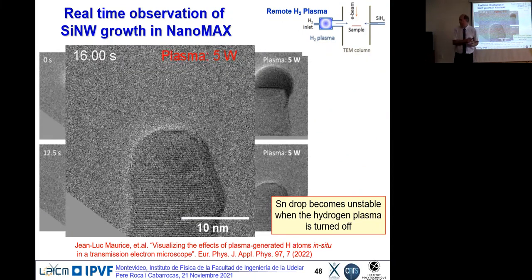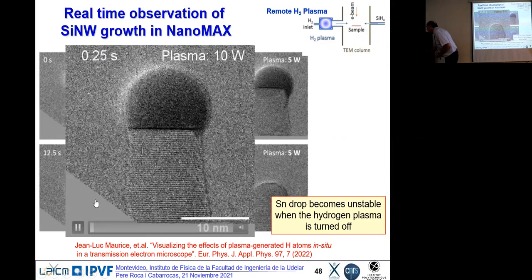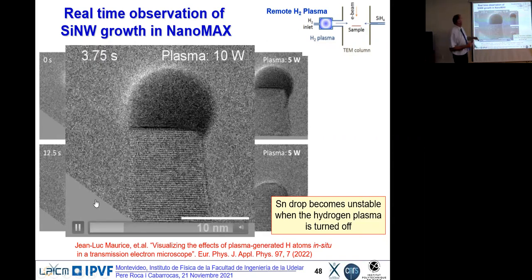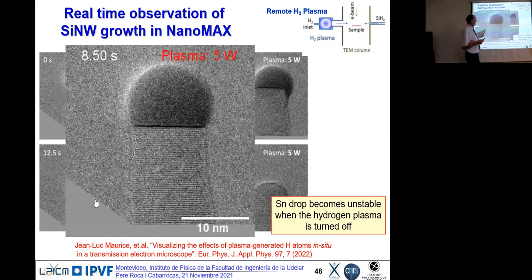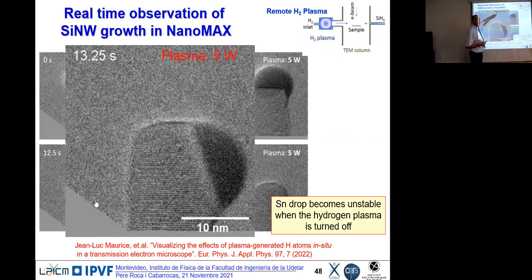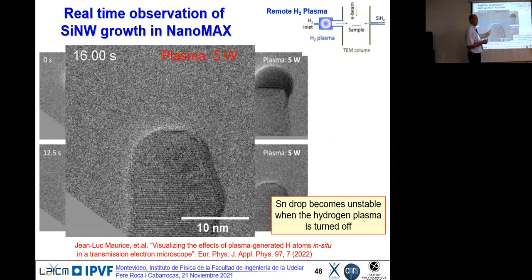Okay, so what happened here? I have to start again, I guess. So at the beginning, we have a plasma power of 10 watts. We have atomic hydrogen, the drop stays on top. If the plasma power goes down, we have less atomic hydrogen. At 250 degrees, the surface energy of the substrate, the crystalline silicon, increases, and the drop falls down. Drop is over.